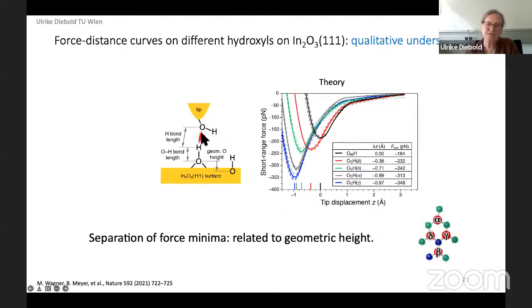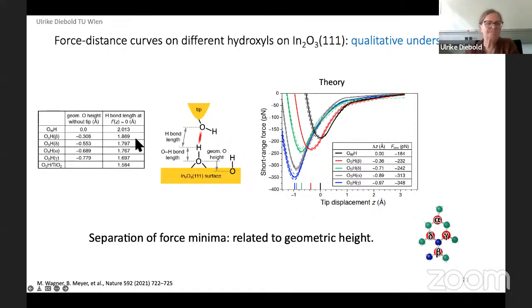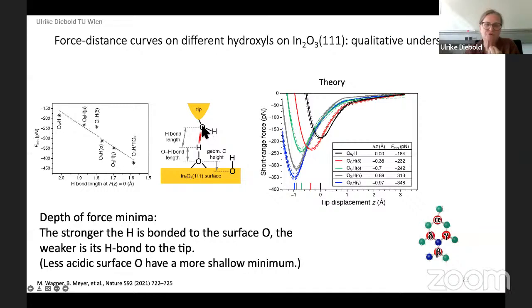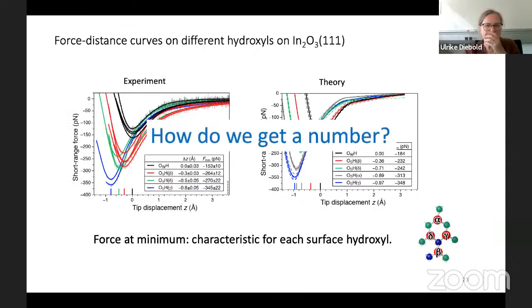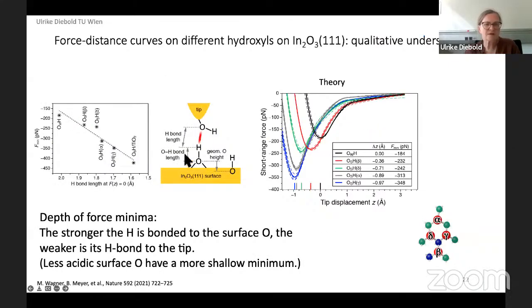So we can change this bond length here, and this geometric height of the hydroxyl. That's what we measure here for the different displacements. But more interesting is this change of the minimum. So the minimum is how strongly does this oxygen atom of the tip interact with the proton on our surface. And really what we have here is, if you take this bond length at the minimum, and you look at the bond length of this hydrogen bond, then there's a nice linear relationship with the force.